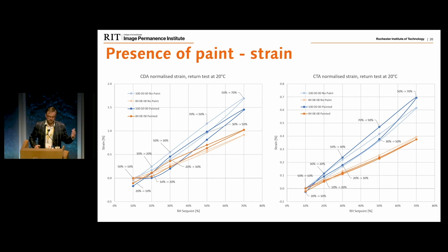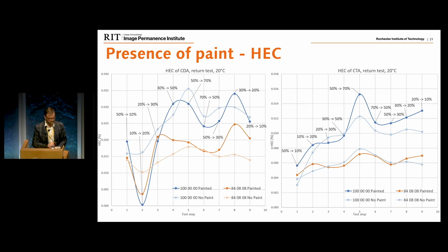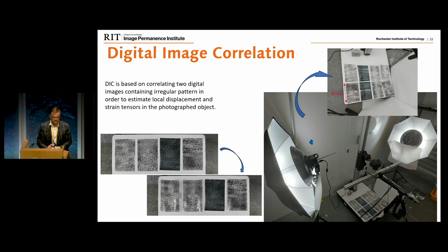So when you're applying the humidification and drying at the same pace, at the same rate of change, you get more stress on the drying side than on the humidification side. And this is very well seen in the humidity expansion coefficient graphs, where you can see those peaks at the end that are actually going higher than the maximum humidification points that we have seen before. Okay, so how does it work out in the DIC, because obviously the objects in real life are not 10 millimeters wide, despite it would make things much easier.